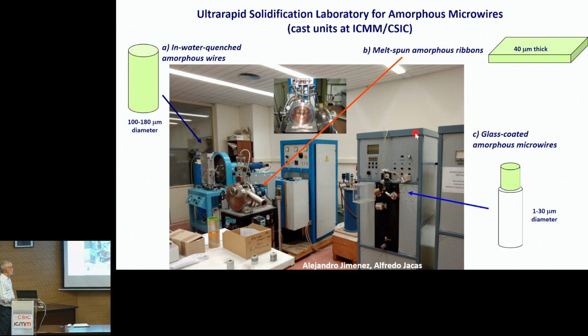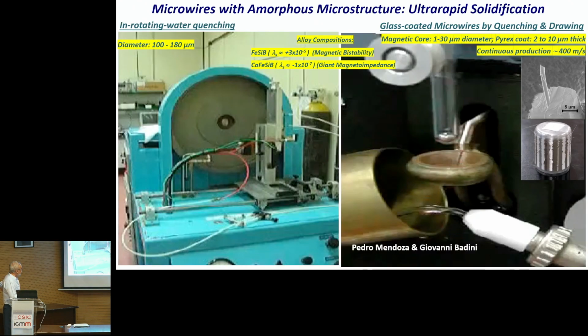This machine originally is from the Soviet Union, but now is much more simplified. I will be talking about the in-water quenched amorphous wires with diameter in the order of 100 microns, and glass-coated amorphous wires with the diameter from 1 to 30 microns, covered by Pyrex. To summarize, in both families of microwires, what is important is the composition.